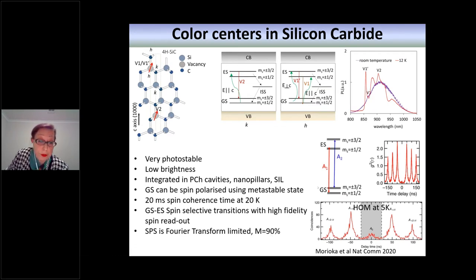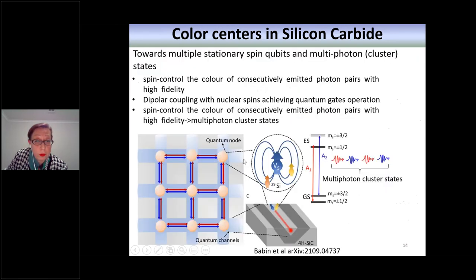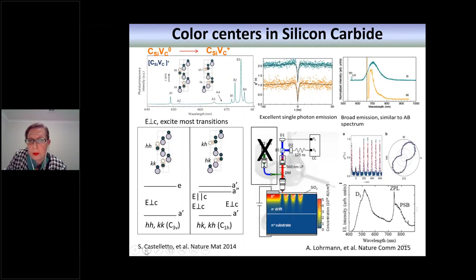It's a very complex defect because it has spin 3/2, but it is very photostable, and it has been integrated in photonic cavities, and the single photons have been found to be Fourier transform limited. In addition to that, it's possible using these defects to create multi-photon cluster states. It has been demonstrated just recently, quantum gates in photonic waveguides, triangular waveguides in silicon carbide, due to dipolar coupling with the silicon vacancy. So this is quite a promising color center.